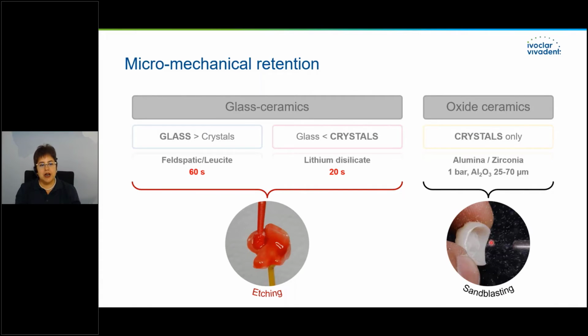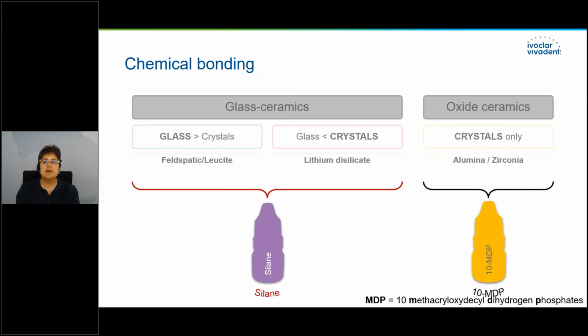And another way how to pre-treat our all ceramic restoration is for the alumina or zirconia restorations. Here we always need to sandblast. Mostly it is maximum with 1 bar and with particle size of aluminum oxide between 25 and 70 microns. The chemical bonding is done on the glass ceramic with a silane. And this is the bonding on the glass phase. On the oxide ceramics, we have no glass phase, so we need a primer which contains the 10-MDP. The MDP stands for 10-methacryloyloxydecyl dihydrogen phosphate.